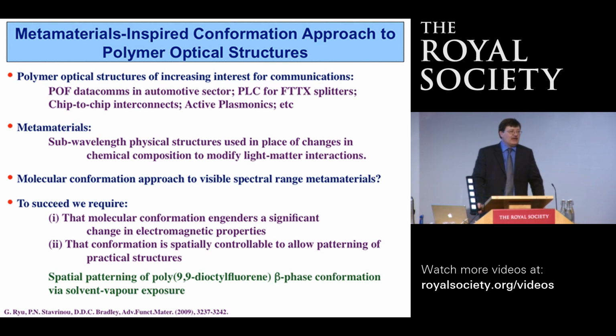What we've thought about is to look at trying to obtain some of these effects in the visible part of the spectrum, where essentially we now need to be able to structure our materials physically on length scales which are short compared to the visible light, so very small length scales, so in the tens of nanometers or less. And basically to think about trying to do that with molecules, and in particular, trying to do it with molecular conformation. So we're coming back to something we talked about earlier in the talk. So the ability to change the conformation of our polymer, if that conformation change also induces a change in the interaction with the optical field, and if we can basically spatially pattern that conformation, then we have the opportunity to make some interesting materials in this area.